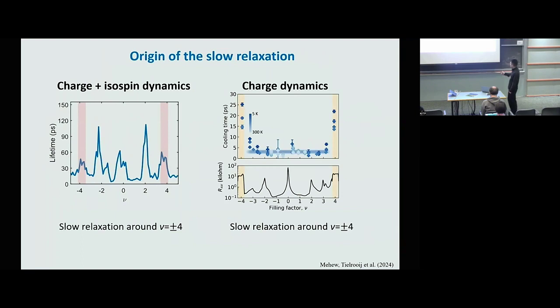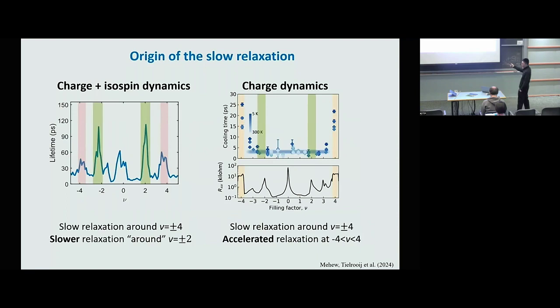And we also see this slow relaxation around plus minus 4. And again, it's probably not surprising. It tells us that it's most likely just a slow cooling of the electron temperature or slow charge dynamics. However, if you look at all the regions between plus and minus 4, then the charge dynamics is actually very fast throughout the whole region. And actually, the main conclusion of this paper is that the charge dynamics of the electronic cooling is accelerated in this whole region because of the Auger process involving moire phonons. So electron cooling is very efficient over this whole region. It's more efficient than non-twisted bilayer graphene.